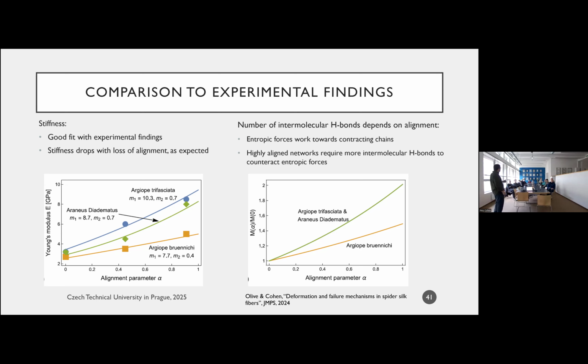If I take this fiber in water and then I stretch it and I let it dehydrate under tension, now I've forced a certain ordering in the material, which means that once it's completely dry, I expect to have a fiber that's much stiffer. And it turns out that it is much stiffer, right? So these different curves are for different spider species, right? I'm never going to be able to say the names of these, so I'm not even trying. But you can see we get different spider species, and our model works pretty well with all of them, right? So we can understand what happens to the different fibers.